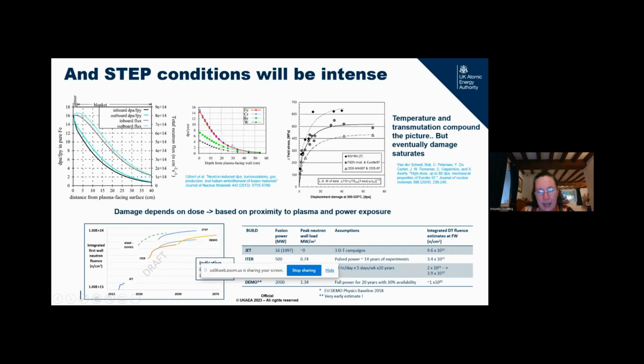And what you'll see is that actually the damage drops off fairly radically once you get away from the first wall. So it is the first wall where we have to concentrate most, and in the breeder zone. When we get back into the magnet shielding and the vacuum vessel, then we have less of a problem on our hands. The other thing that I can say to you is that we do know that the damage saturates.